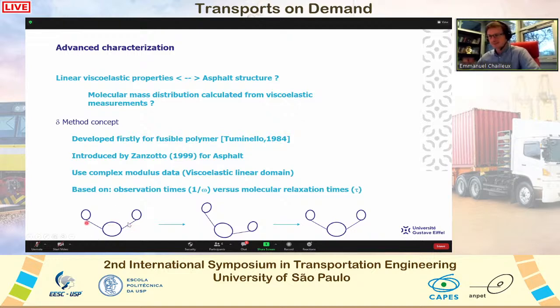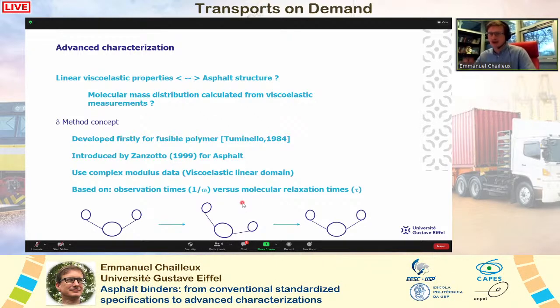Here you can see a sketch of molecules which are loaded and unloaded, and the relaxation time represents the time for the molecule to come back to equilibrium. So the main concept is based on this. If observation time is short, or high frequency, in comparison to the relaxation time, so the time to come back to molecular equilibrium, then the molecule appears to contribute to elasticity. At the opposite, if observation time is very long in comparison to the relaxation time of the molecule, then the molecule appears to not contribute anymore to elasticity, but to viscous behavior.